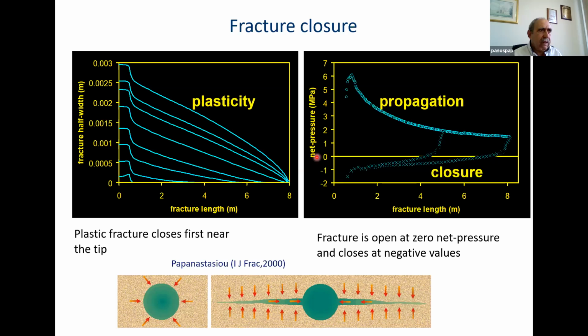In the diagram here, I have the net pressure actually during propagation, which was like that, and then I allow the fracture to close after it had reached 5 meters, like that. And I propagated the other one, and I allow the fracture to close after it had reached 8 meters. Again, you see a great pressure drop when we stop pumping without changing the fracture length. And then the pressure drops and the fracture closes completely at negative net pressures. So if we interpret the closure stress from this point, we will underestimate the net pressure.